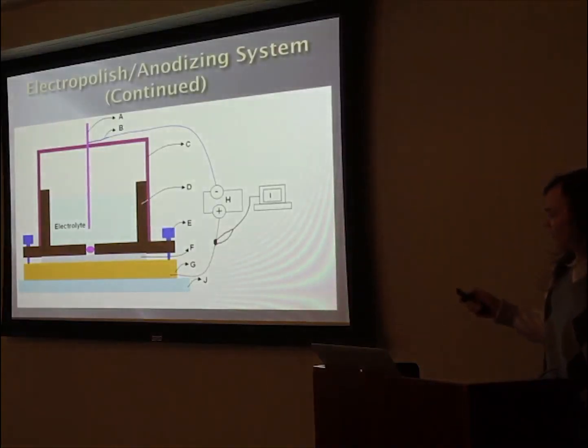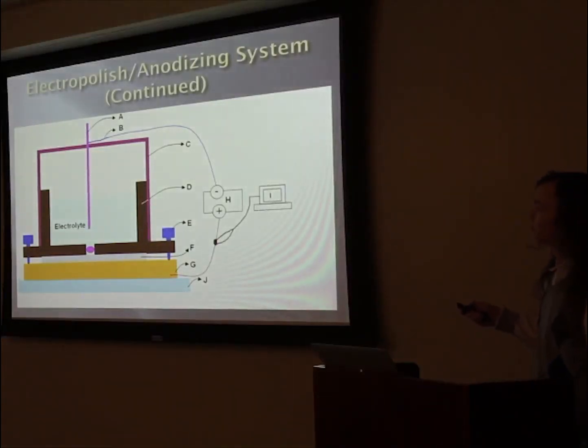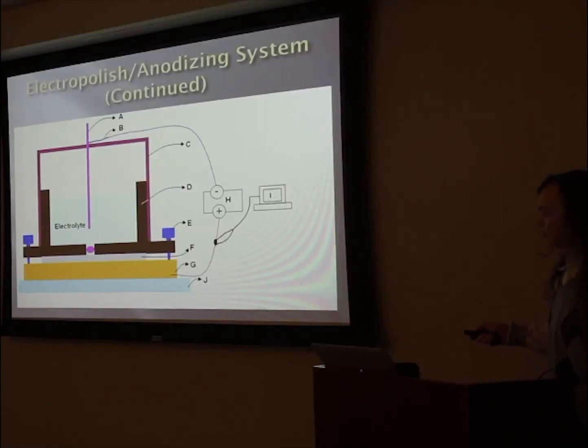So a cross-section of this sample here would be this here. So the bottom here is just your surface you put the container on. This bottom part is the metal holder that we were shown before. This is our sample, a magnetic stir, your electrolyte or acid. And this right here is a platinum wire that you can put into your acid. Because if you put something like copper or anything like that, that's going to corrode inside of it. Platinum is going to last through this process even if you're putting it in an acid.